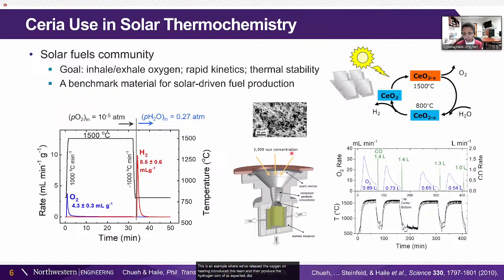We did a demonstration with an actual solar furnace. This was a simulated sunlight, but still very close to what you would do in a real solar concentration scenario. In this case, we were demonstrating CO production, where we were providing CO2 as the reactant gas. And then again, as a consequence of oxidizing the oxide, the released gas is now carbon monoxide, which becomes a component for making liquid fuels.